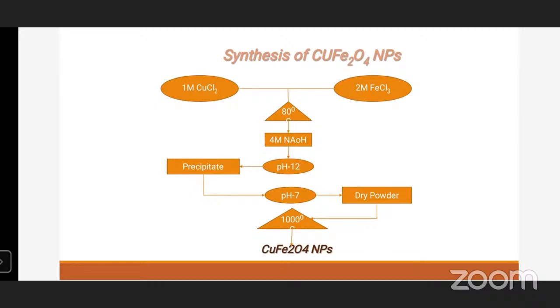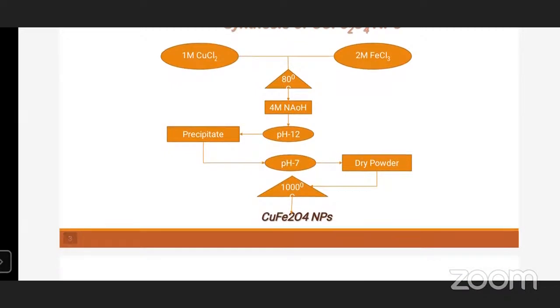At this stage, a slurry precipitate was formed, which was washed several times till the pH of the sample reached 7. Then the precipitate was dried to obtain powder. Finally, the synthesized precipitate was annealed at 1000 degrees Celsius for about 5 hours. Again, the sample was crushed using mortar and pestle, and fine particles were obtained.